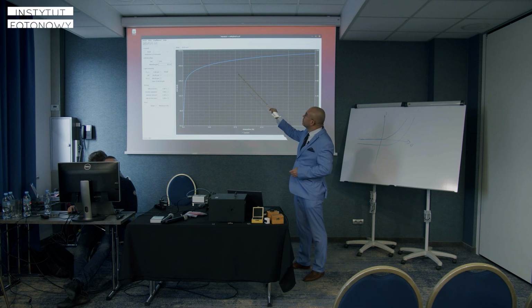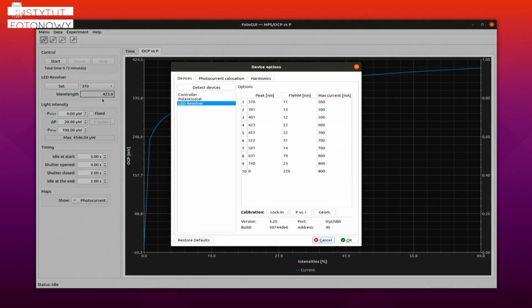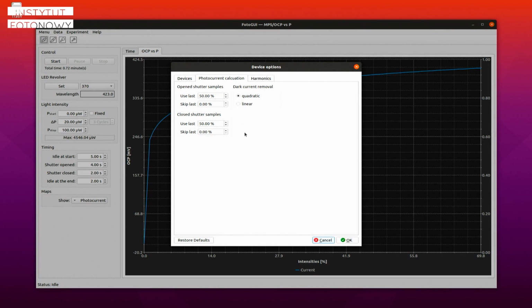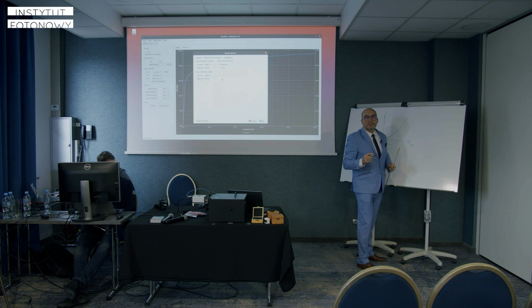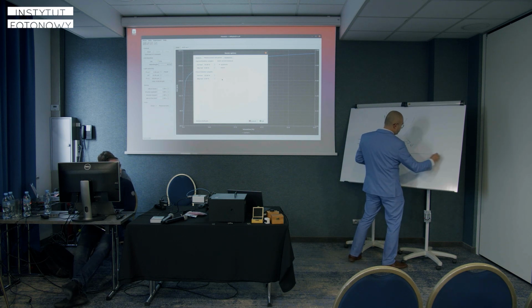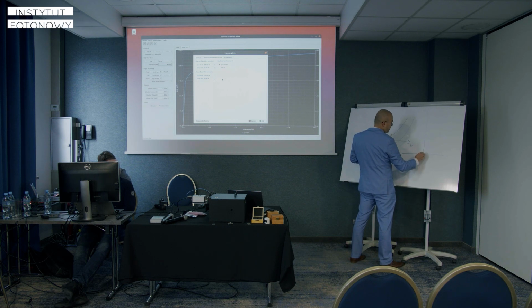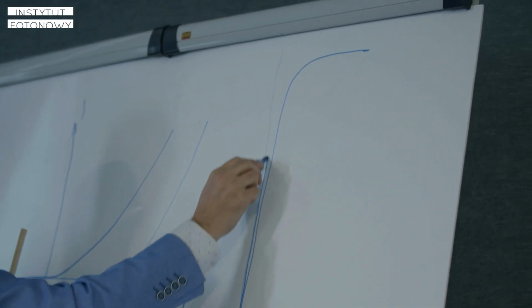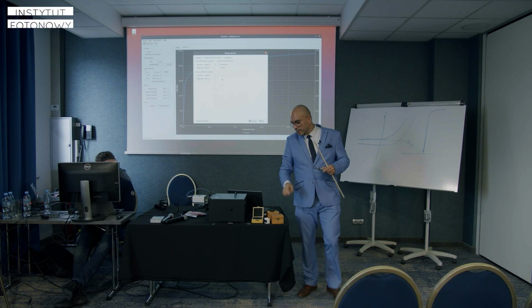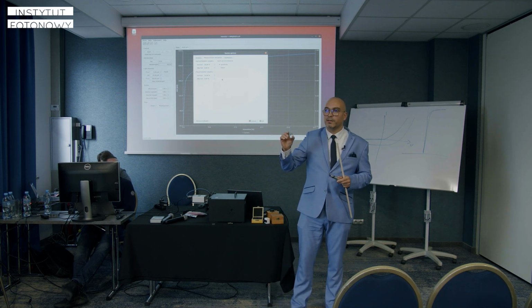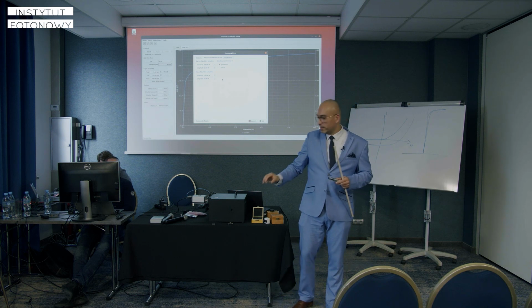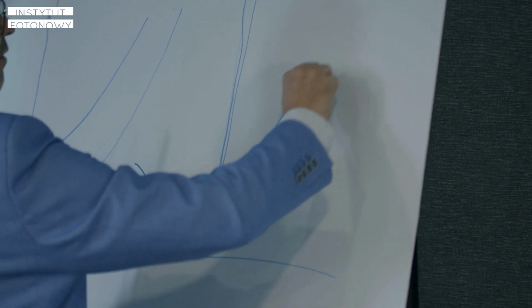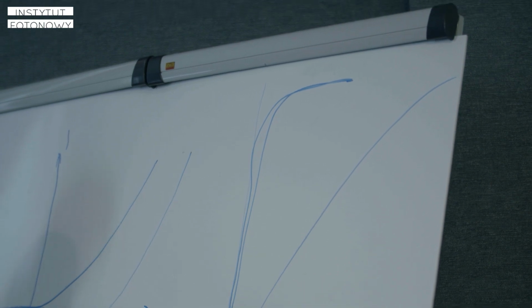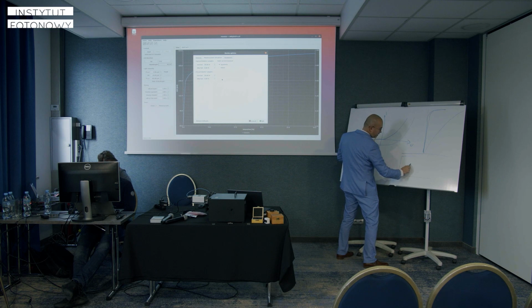Let's go to the menu, devices, second tab, photocurrent calculation: use last 50% and skip last. If we work with a fast sample, like a silicon photodiode, the response when we switch on the light is fast. It's almost rectangular. But if we work with a slow sample, like a dye-sensitized solar cell with a larger capacitance, the sample is much slower compared to the silicon photodiode, and it saturates after, say, 5, 10, 15 seconds.